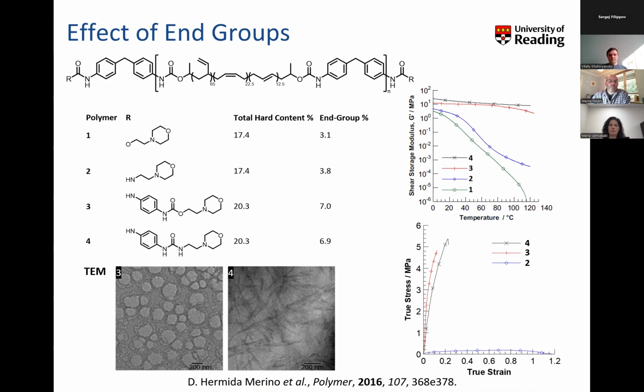So we don't tend to see, across the temperature range that we've studied before, this fall away into the viscous domain. But as a consequence of that, the materials are far stiffer, but not as elastic in nature. So again, with polymers, if you make them stiffer, they tend to be less elastomeric. If you make them more elastomeric, they tend to be less stiff.